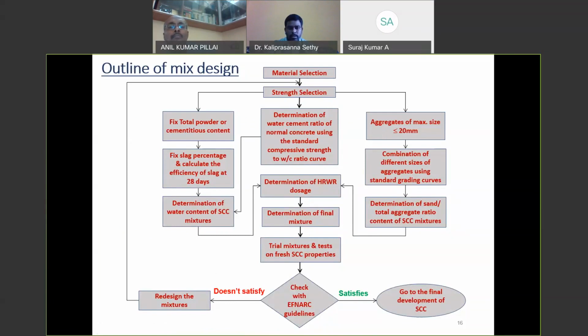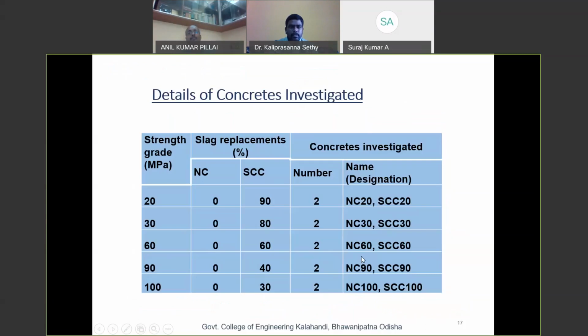and we conducted trial mixes at our laboratory. Once we get satisfactory results for the trial concrete, we can finally go for the development of self-compacting concrete. If not satisfied, we have to redesign the concrete. And this is the mix details of the concrete investigated for this project. You can see strength grades of 20 to 100 MPa we have designed for both normal and self-compacting concrete. For 20 MPa concrete we have replaced the slag up to 90%, whereas for 100 MPa we have replaced the slag up to 30% only.